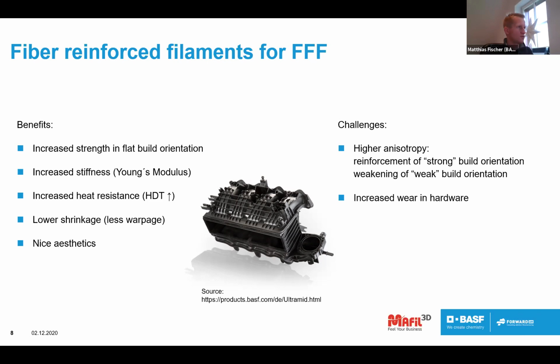And we also have lower shrinkage due to the fibers. A nice side effect is that the aesthetics are also improved, because you have a nice black surface, slightly rough, which is nice to have. The layers are not as visible as usually in 3D printed parts. Of course, this fiber reinforcement also leads to several challenges. You will definitely get a higher anisotropy of the part. These fibers are nice for the flat orientation, but you definitely have challenges in the upright orientation.